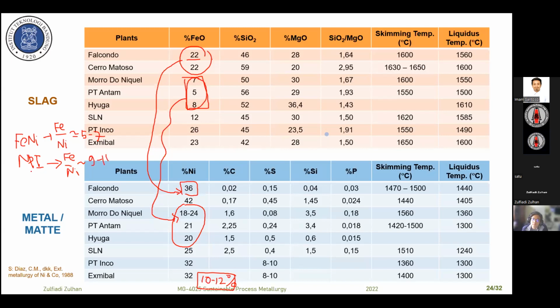In this case, the nickel content is around 10 to 12%. In this case, the nickel content is around 20%. We can adjust by mixing, by blending one ore with the other ore, and sometimes the limonite ore is also blended with saprolite ore.